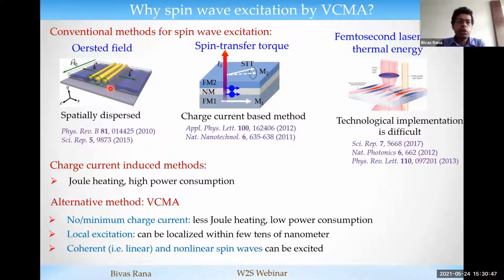a spatially non-uniform magnetic field like this. Then at the resonant condition, it couples with the spin wave having a wavelength of the same order of this nonuniformity, and that's how you can generate the spin wave. But the problem with this method is that the Oersted field is spatially dispersed.